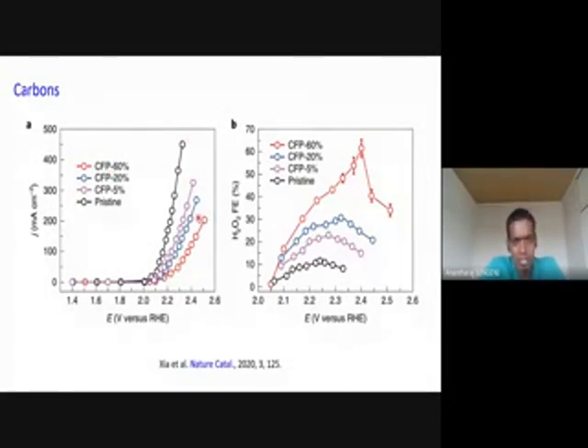They attributed this to the trapping of evolved oxygen gas within the layer of PTFE and carbon fiber paper. So this was the first report in which they showed the influence of trapped oxygen for improving H2O2 selectivity. Relatively, H2O2 evolution from water oxidation has a very low number of reports, but it is expected that it will be blooming very rapidly in the near future.